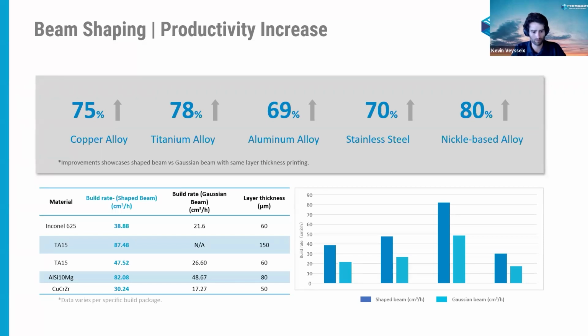And here you have some data explaining, for example, with aluminum, 80 micrometer layer thickness, we had almost 50 cubic centimeters an hour per laser with Gaussian beam. And now with shaped beam, we are more than 80 cubic centimeters per hour. So you can imagine we still have room with the laser power, and we are just at 80 micrometer layer thickness. So it's just a matter of time. We can easily reach more than 100 cubic centimeters per hour.